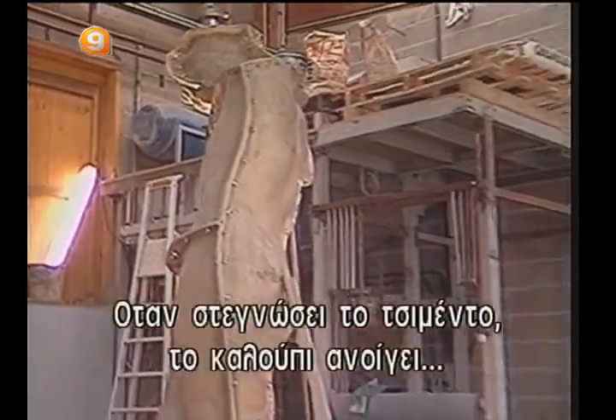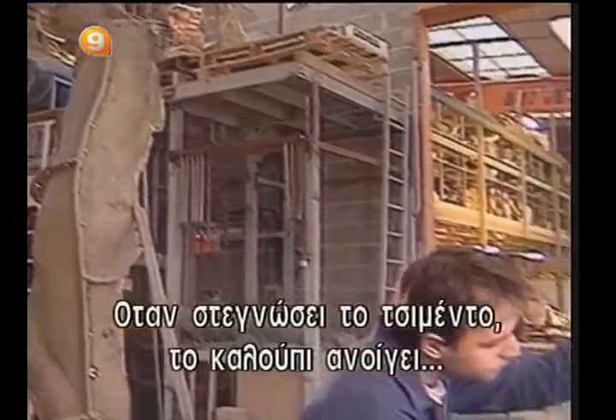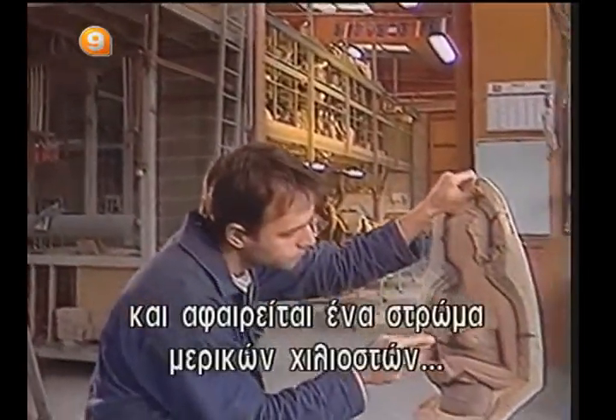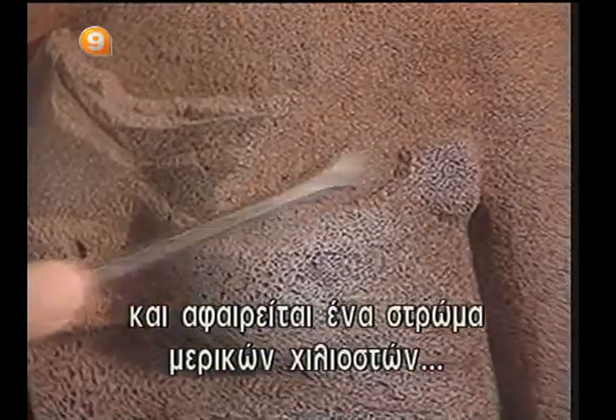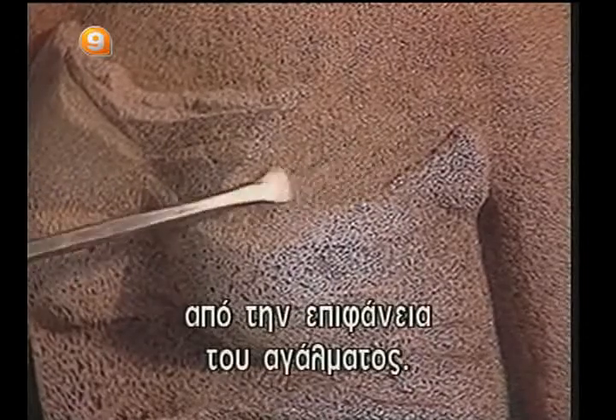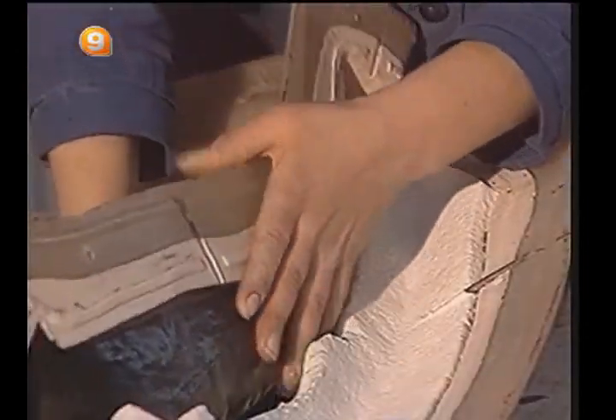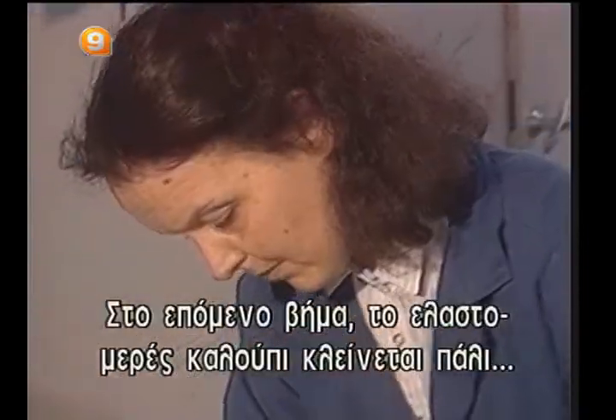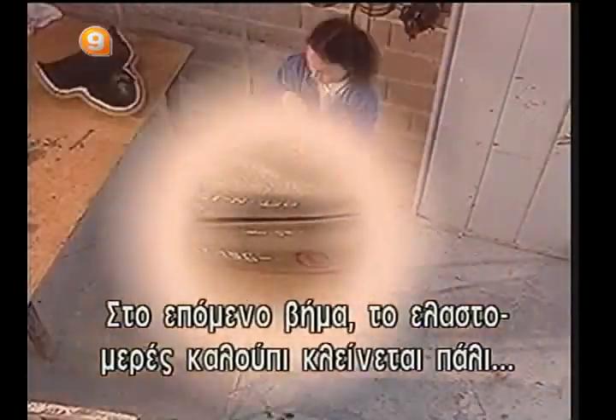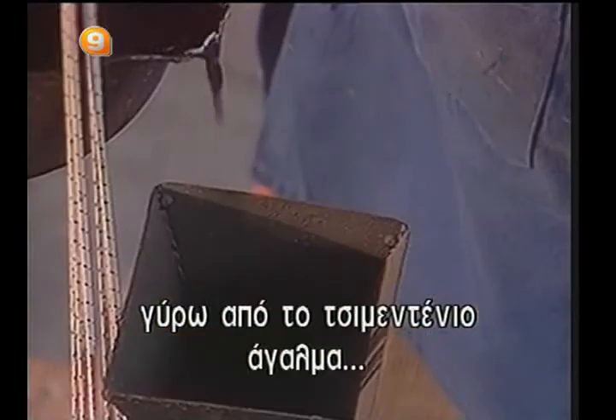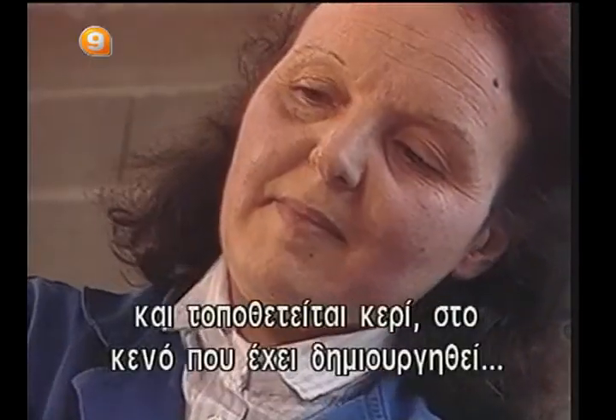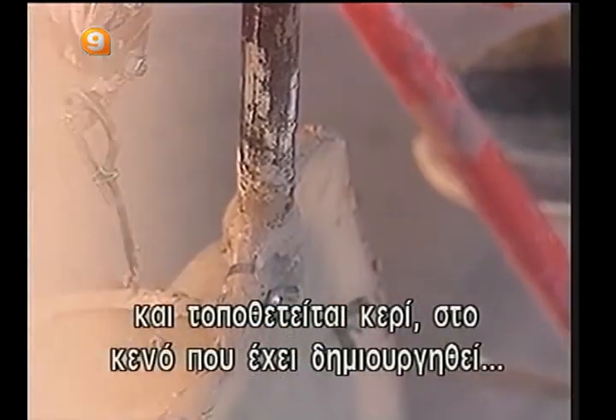When the cement forming the mold is dry, the mold is opened, the core is taken out, and a layer a few millimeters thick is scraped off. In the next step, the elastomer mold is closed over the cement core again. Wax is then poured into the cavity between the mold and the core.